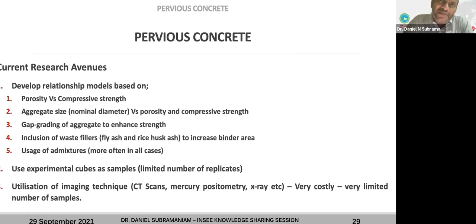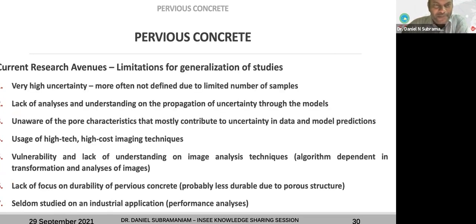The other problem that we found with this image analysis is that converting the image to a binary or tertiary system itself involves a lot of algorithms, and the algorithms have a lot of issues with uncertainty, because then you are playing with the uncertainty a lot. You are compromising by either overestimating or underestimating a pore. You will not be able to get the correct pore sizes because of the color codes and so on. So we thought, and we actually have used, imaging technology using the normal digital cameras that we have, but we had to do a little bit of preparation of the samples.